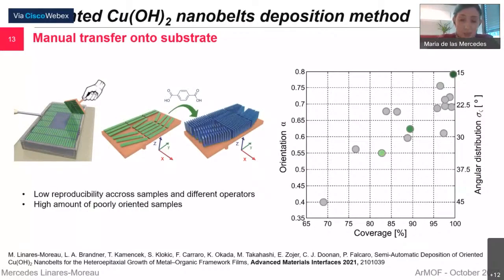So with this in mind, we prepared many samples with the typical manual procedure, and we observe that around 50% of the samples have an orientation that is below 0.7. That could be our threshold for the quality that we want to have, with a wide range of inhomogeneous coverage, let's say. Ideally, we would like to be in this top corner with the highest orientation and the highest coverage. And importantly, this is also very operator dependent.